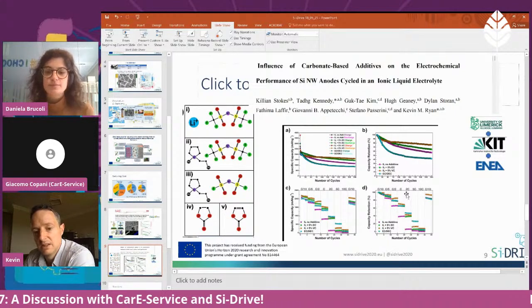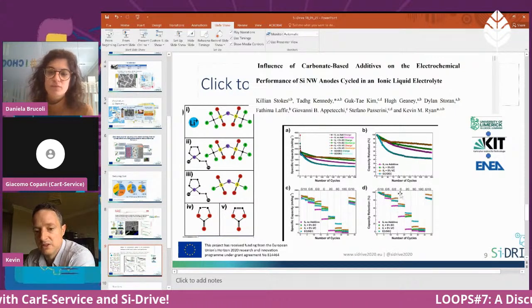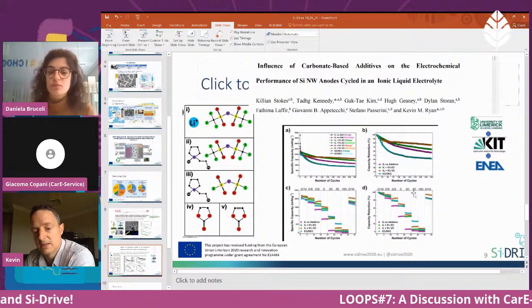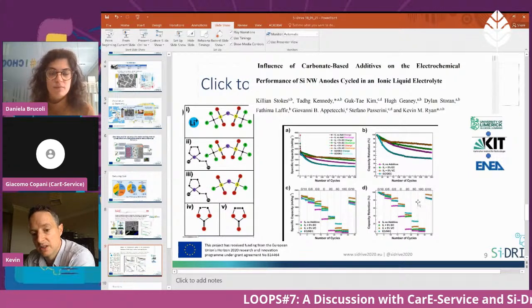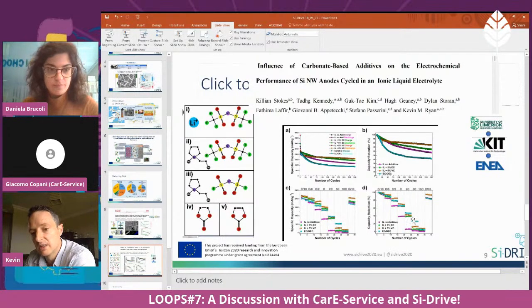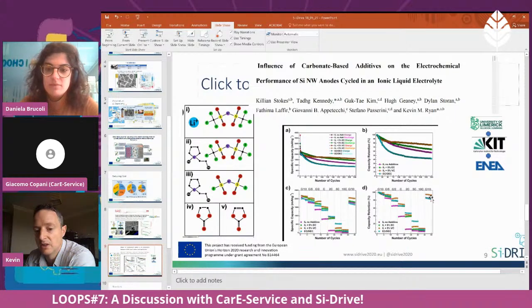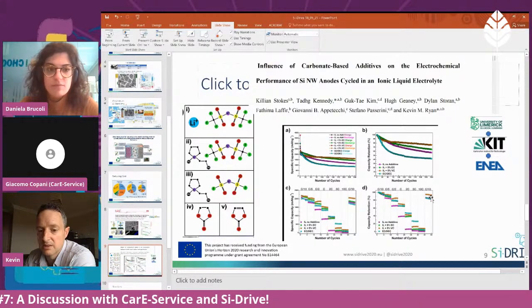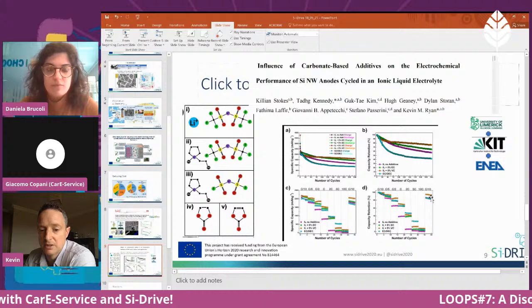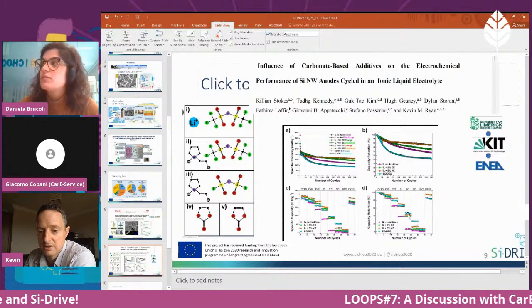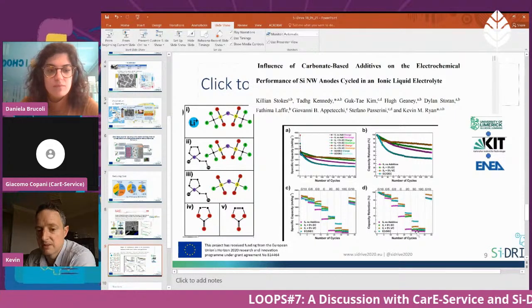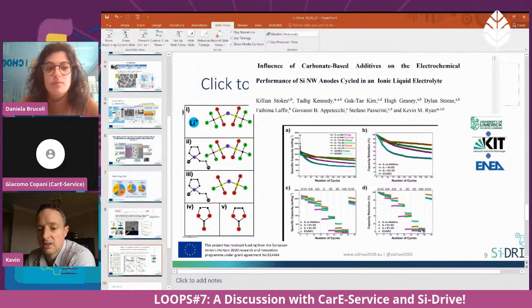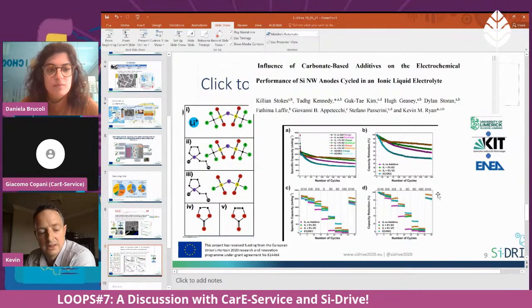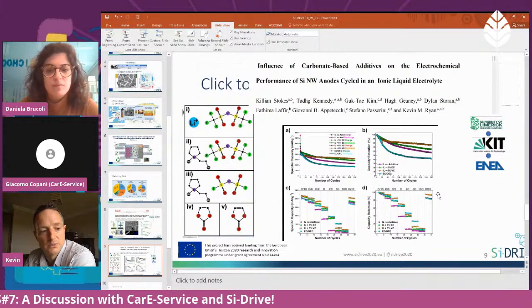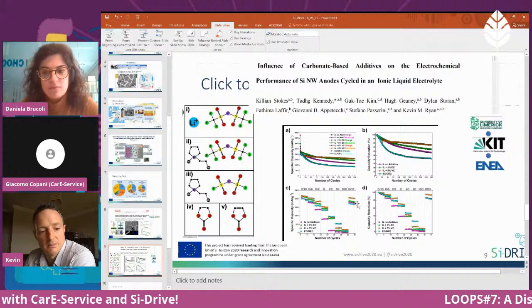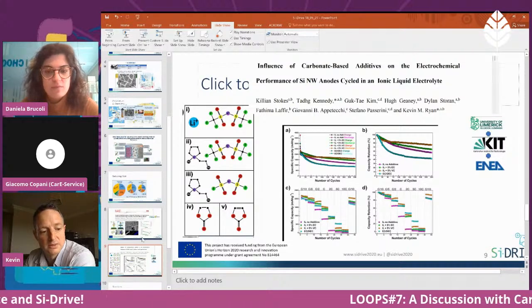And then we can see the performance at different C rates. So we can see, for example, that as we go through C, 2C, 5C, and then back to C over 10, you get a lower capacity, which you'd expect, but you recover that capacity when you go to higher C rates. And in actual fact, if you compare this to graphite-based materials, they would not be able to perform at a similar level. So you would not be getting any capacity at a very, very fast charge and discharge, and you wouldn't regain that capacity when you return to the lower charge discharge rates.